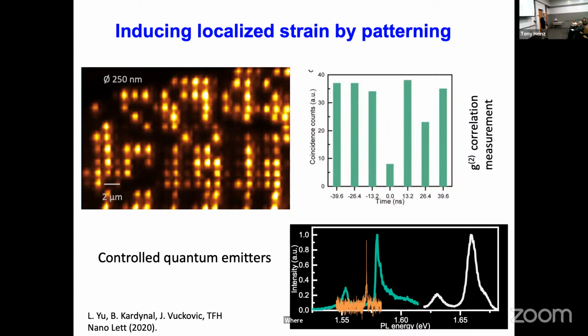But what isn't so easy is this: if you try to make the same depth of well, there's a very easy scaling relation. You more or less keep the same aspect ratio. It turns out, however, that it gets harder and harder to pressurize it and make the film bend. The pressure needed scales like the inverse of the diameter. So it's extremely easy to pressurize a 250 nanometer one, and it gets harder and harder as you go down.